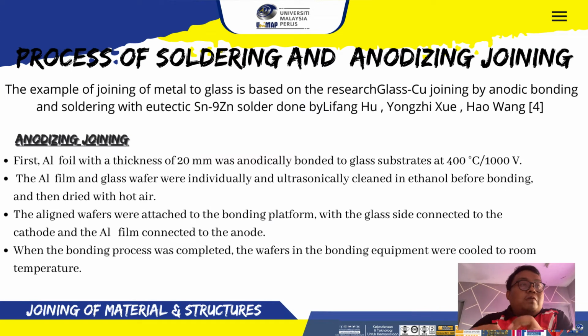This is an example of joining metal to glass based on the research on glass copper joining by anodic bonding and soldering technique done by Lifang Hu, Yongzhi Xue, and Hao Wang. Okay, for the anodic bonding, first, aluminum foil with a thickness of 20 mm was anodically bonded to a glass substrate at 400 degrees Celsius and 1000 volts.